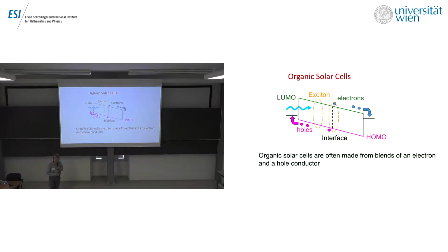So they move through the material as excitons. They cannot be dissociated by thermal excitation. And the only way you're going to prise the electrons and holes apart is when the exciton finds an interface between two materials, at which point it gains the energy to dissociate. And your separated charges, if you're lucky, will find their way out of the device and create a current. If you're lucky, that's referring to the fact you will get a lot of recombination.